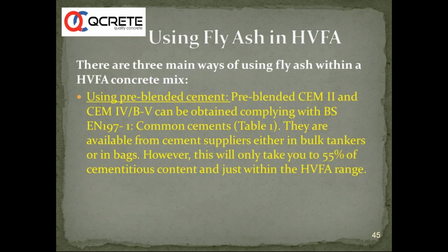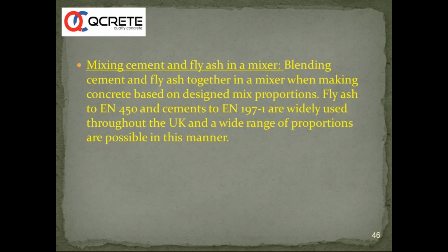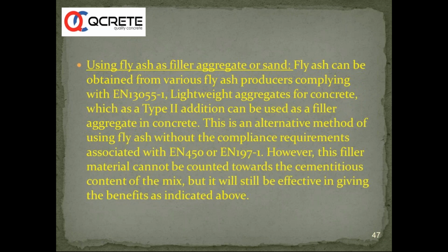So we are surprised to see that high volume fly ash can be used in pre-blended cements. Some countries in Europe, they're blending in different ways, different proportions, and making fly ash based cement actually. High fly ash amounts are used actually. You can blend it in cement, you can blend with concrete, and then you can also use it as a filler actually. For example, a specification like IS 3812 says we have to use 15 to 35%. You can use extra amount of fly ash as a filler, as a replacement for sand if you don't have a good sand, and we can reduce the water cement ratio and make good concrete actually. So fly ash can be used as a filler material instead of sand.